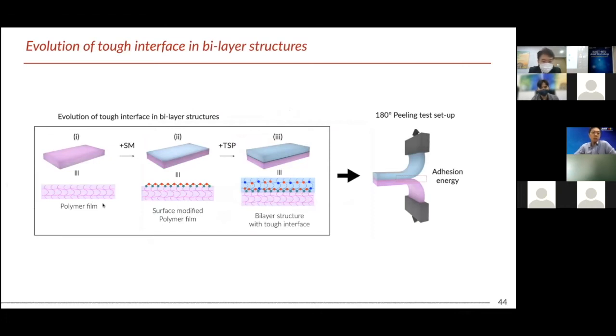So for polymer films, if there are different surface properties, they cannot be entangled and they try to separate, so they show very poor adhesion. So my principle is, in order to make the topological adhesion between the two surfaces, just modify the polymer film with some certain non-covalent interaction.